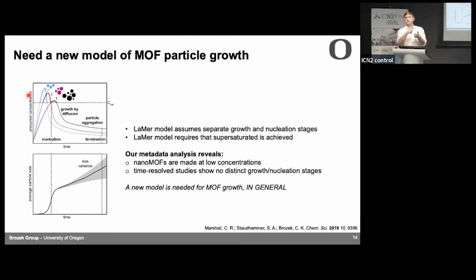Well, the LaMer model assumes that you're working at really high concentrations, and it assumes that there's a separate nucleation and growth stage. And when we were doing this metadata analysis of the literature, we noticed that often nanoparticles of MOFs are made at concentrations that are much lower than the bulk synthesis. So that was unexpected. The second thing is there's some nice in situ studies watching MOF particles grow, which suggested that there aren't distinct growth and nucleation steps. It's just sort of like a continued, almost like a polymer growth. And so we decided that we would need a new model to understand how MOFs grow.